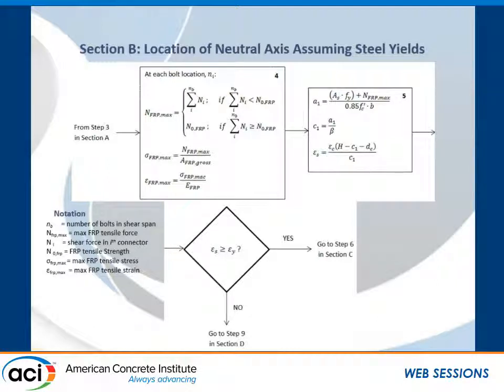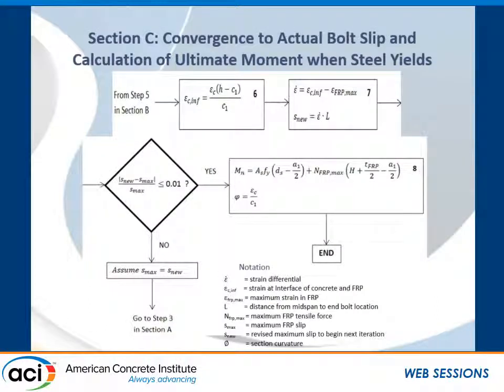And we need to verify the assumption that the steel has yielded from strain linearity. Let me note that if the steel does not yield, and it's possible that it doesn't, then the neutral axis is relocated before we calculate our interface strain, which is what we see on our next slide. So the strain at the interface of the concrete and the FRP is calculated.